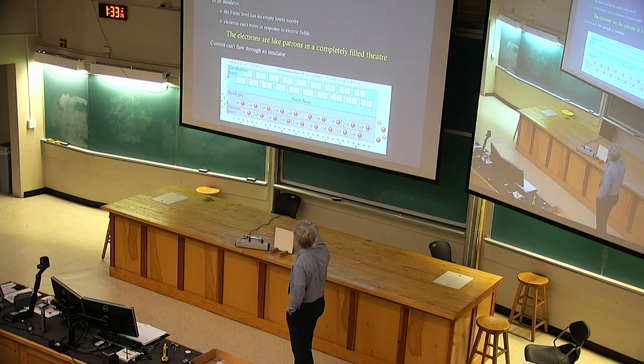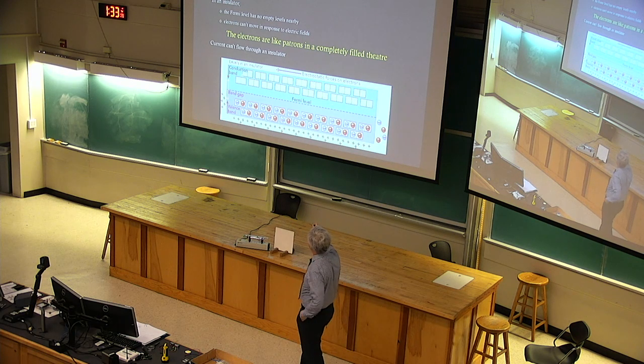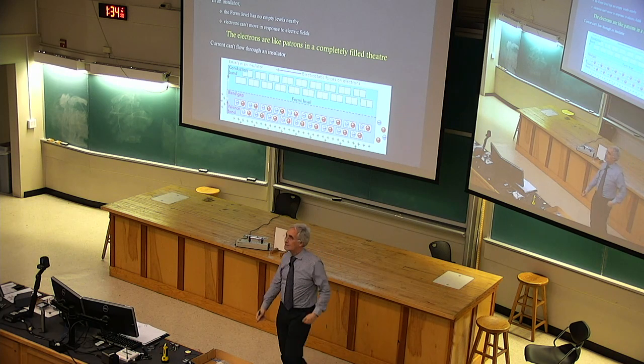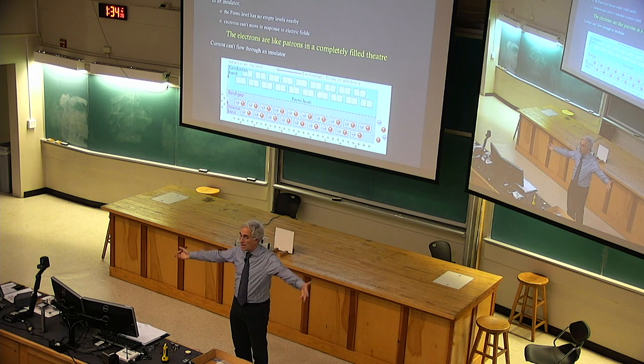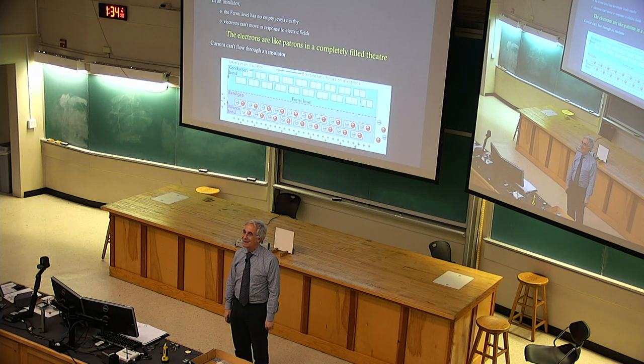We've filled all these levels down here in this band of levels, the so-called valence band, and we have not yet filled any of the levels. There are no electrons in these standing waves of the conduction band, and the Fermi level is in between. And the fact that it's in between, with a huge energy desert above it and below it, means that this isn't going to conduct any electricity. All right? Any questions about insulators and metals?